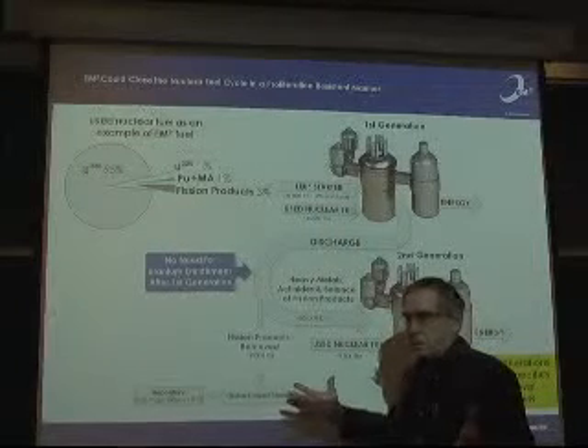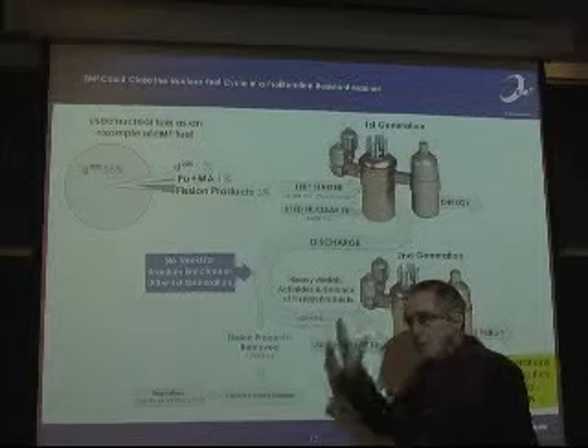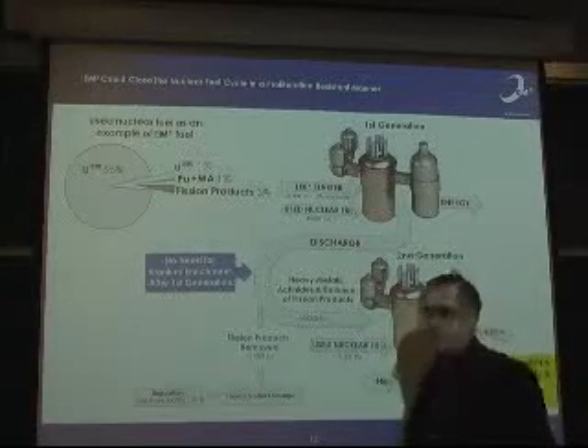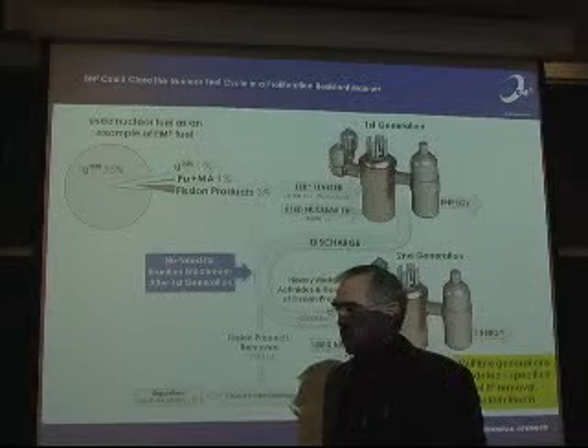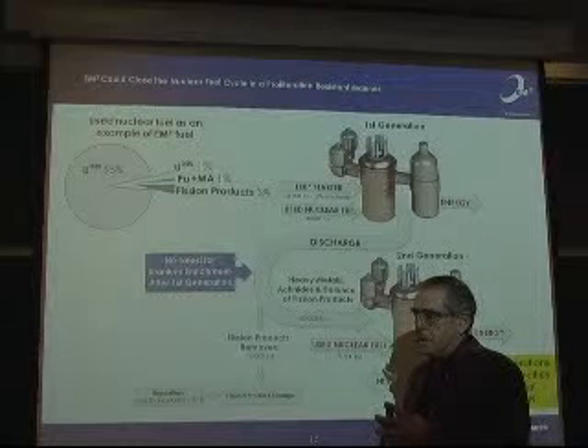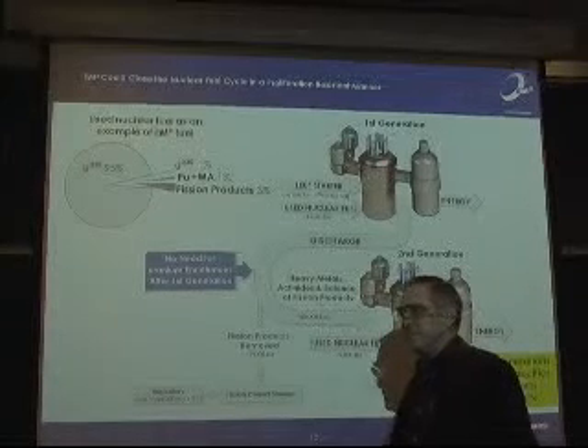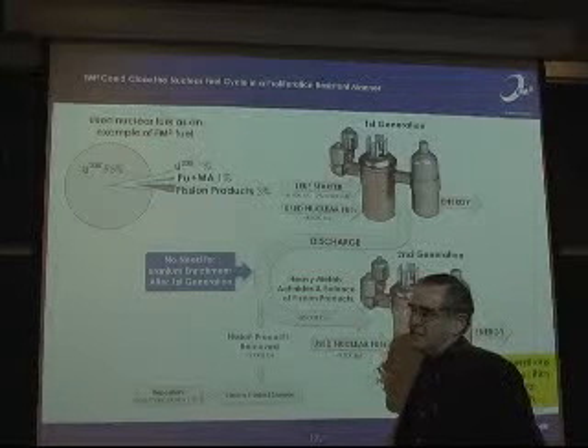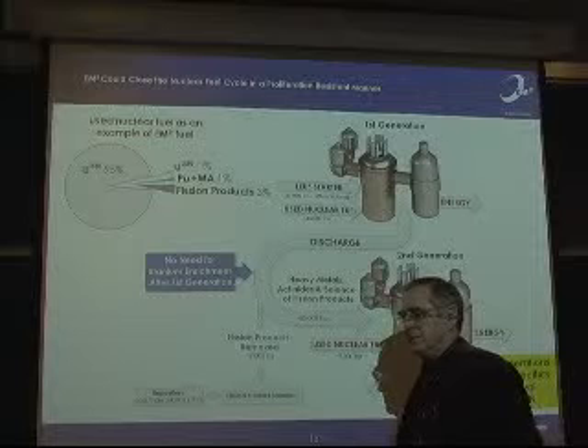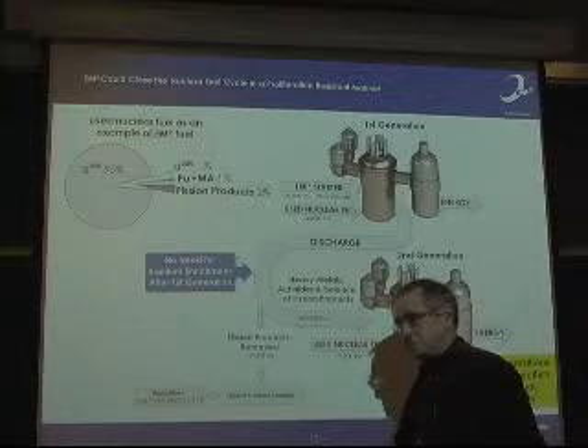Now, if you use used nuclear fuel, you don't have to take the fission products out at all. Because this is a fast reactor, those fission products have negligible negative reactivity, and all you have to do is just refabricate that fuel and put it in the reactor. That's the interesting thing, because this fuel has plutonium in it, and it compensates for the negative value of the fission products in a fast spectrum. But it's only 1% plutonium. And then it has about 1.5% uranium-235. And it has about 5% fission products, which are not worth an awful lot in the fast spectrum.